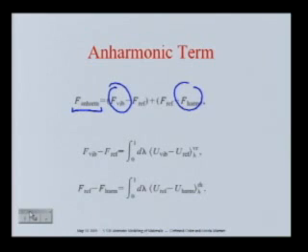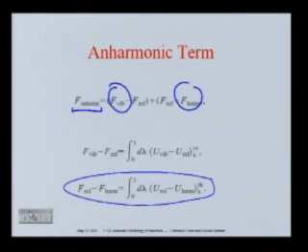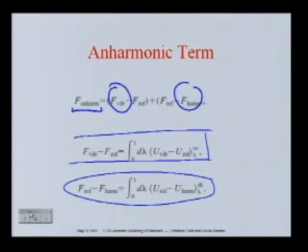You want the phonon spectrum, and then you need to do a number of molecular dynamics simulations, very extensive for the classical potential, and then you just correct your classical simulations with the difference between the classical and the quantum potential. And once you have all of that, you are basically able to calculate all the free energies that you need.